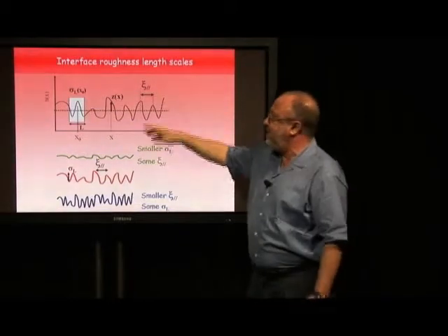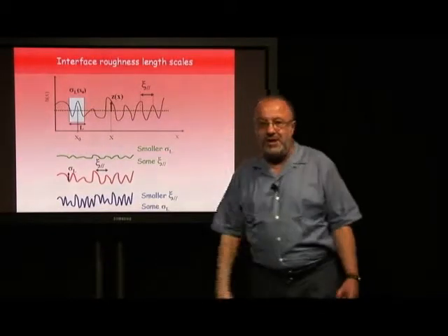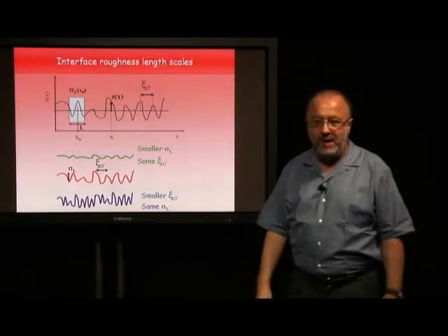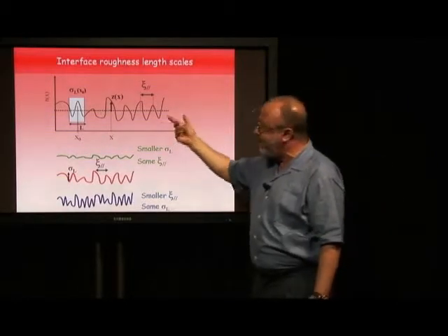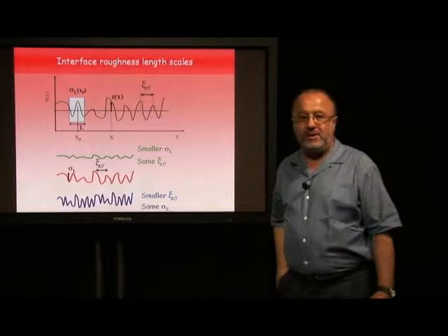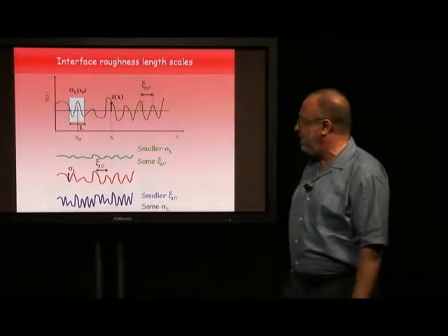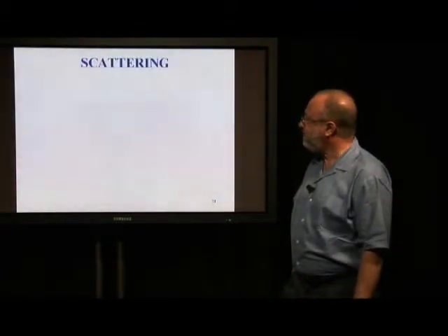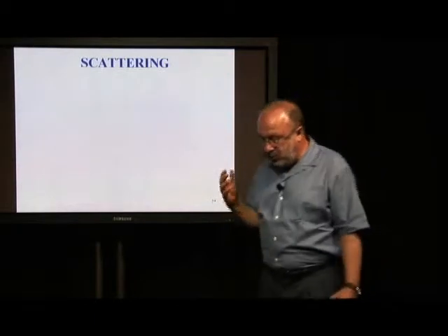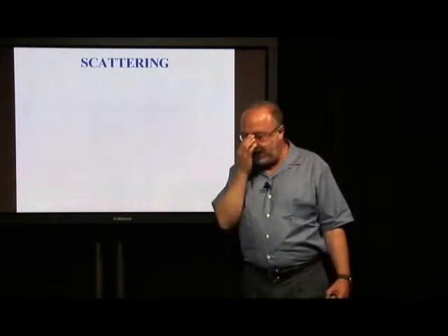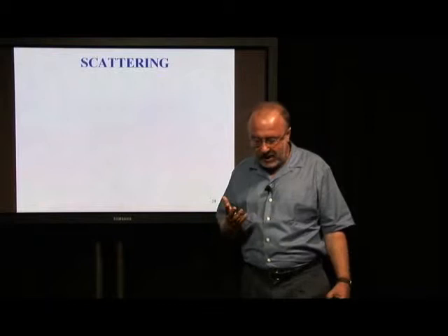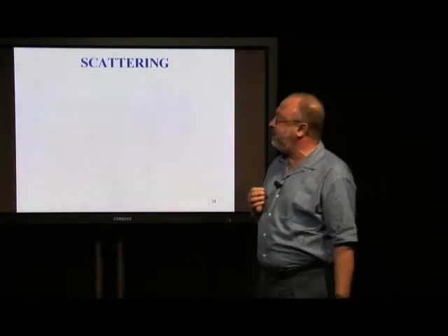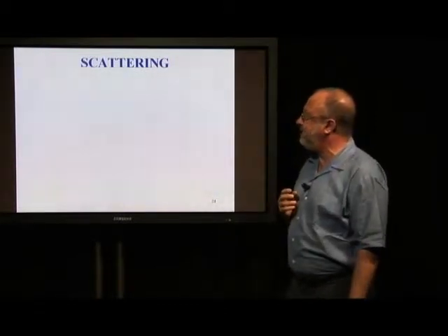There is all this roughness, there is interdiffusion, there are all kinds of issues that you have to deal with, and all these different types of property changes at the interfaces between these materials will affect the properties quite substantially. So to characterize these materials quantitatively, one does what is called scattering, and it's one of the key methods. In particular, X-ray scattering is what we do.